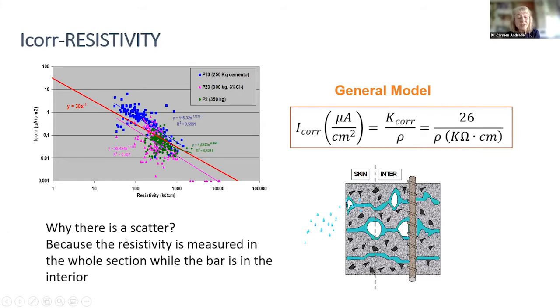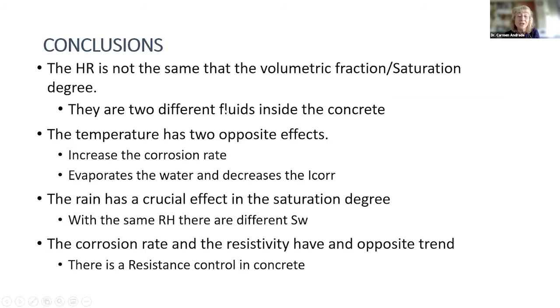And why the scatter? Again, because we measure resistivity in the whole volume, while the corrosion rate is just near the bar. In that case, it has to be an average of the resistivity that is not the average that we measure at the bar. In any case, we have this equation that we derived from the previous lab experiments, and that is confirmed, we think, after many years of measuring.